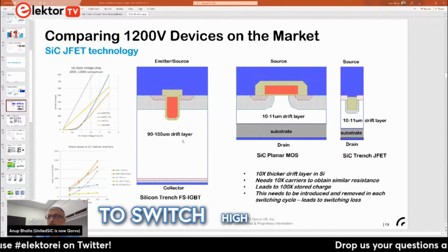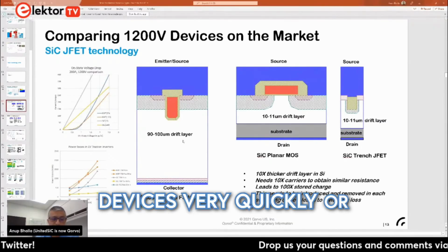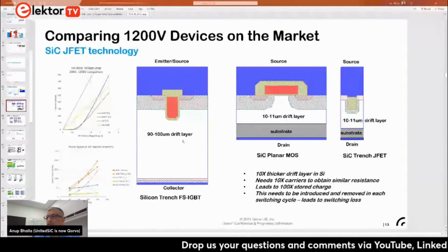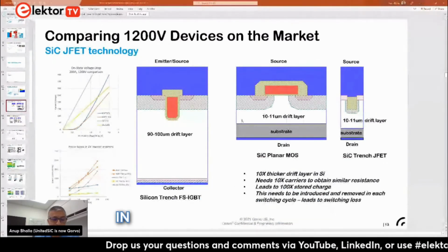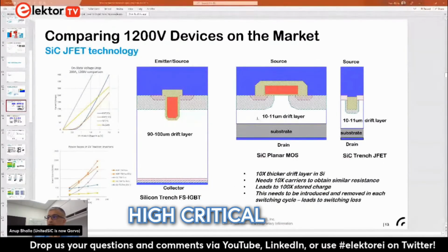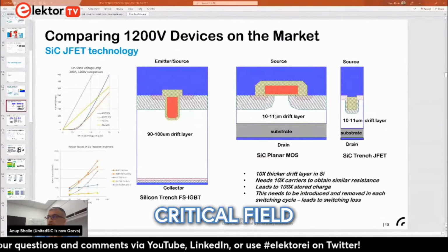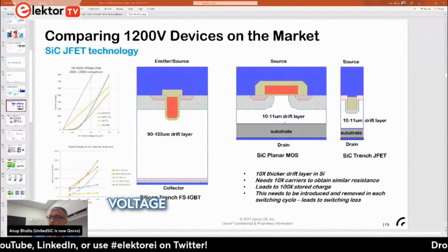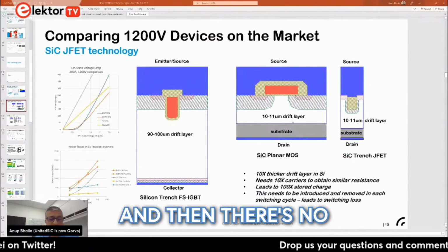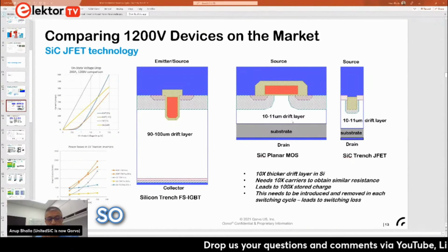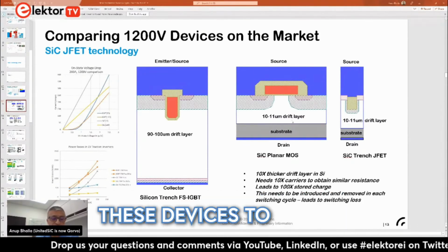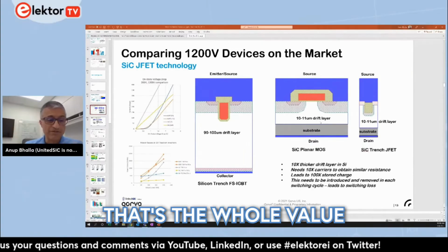So if you wanted to switch high voltage devices very quickly or losslessly, this is where wide bandgap devices come in, because with their high critical field, like 10 times higher, you can theoretically have a 10 times thinner region to support the voltage like I'm showing here. It's called the drift layer. And then there's no need to inject carriers anymore. So you're just charging and discharging capacitances. And this allows these devices to switch much faster. So that's the whole value proposition for wide bandgap devices.